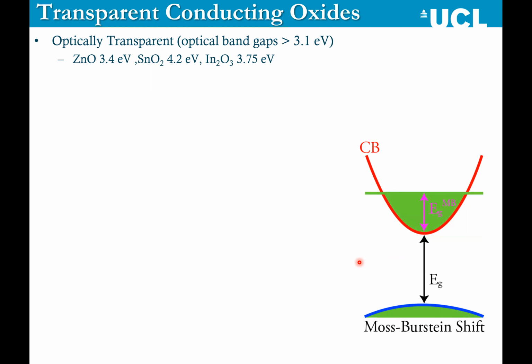For really good N-type transparent conducting oxides, your excess electrons in your system will actually occupy the bottom of the unoccupied conduction band, filling it up with electrons up until this green point here, which is the Fermi level. So essentially your optical band gap becomes the EG, which is the fundamental difference between the valence band maximum and the conduction minimum, plus this EG-MB, which is the Moss-Burstein shift, giving you the total optical band gap. So you can basically take a material that might not have an EG bigger than 3.1 electron volts, but you can dope it to make it optically transparent.